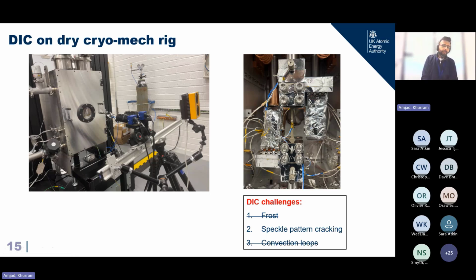So moving on to the even lower temperature, specifically talking about close to 10 Kelvin. We have this rig which does cooling of the sample through conduction using GM cryocoolers. I have a picture of the inside of the sample. We've got some temperature sensors mounted onto the sample, and it has a window, so we can do stereo DIC on it as well.